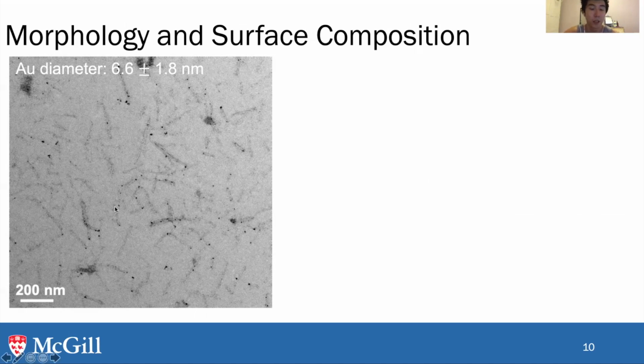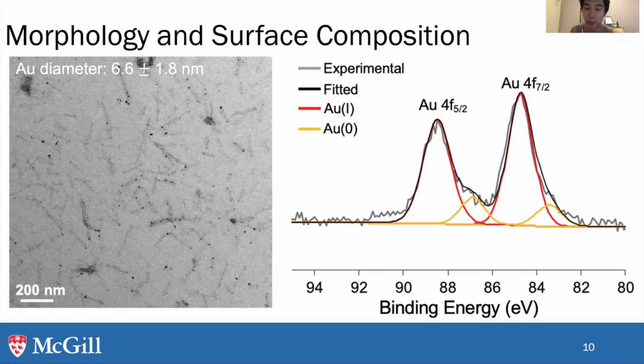So we also did some surface compositional analysis using X-ray photoelectron spectroscopy. And from this, this is a surprising result, because you can see here that the main oxidation state of gold is actually gold 1 instead of gold 0, which you would normally see for gold nanoparticles, which means that most of these black dots here are aggregates of gold 1 and not metallic gold. And so what this implies is the hydrogen reduction procedure doesn't fully reduce the gold into gold 0. And we're getting, instead of metallic gold nanoparticles, gold 1 aggregates into nano dimensions.